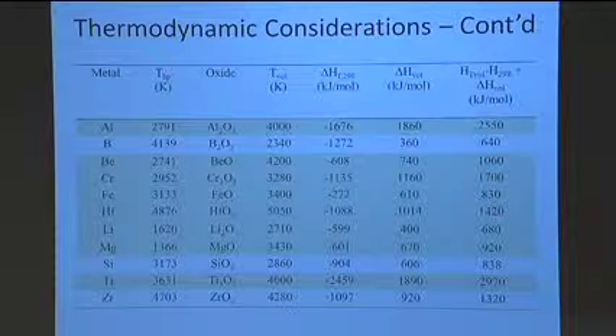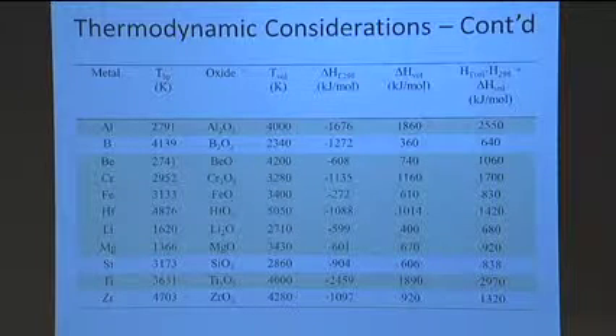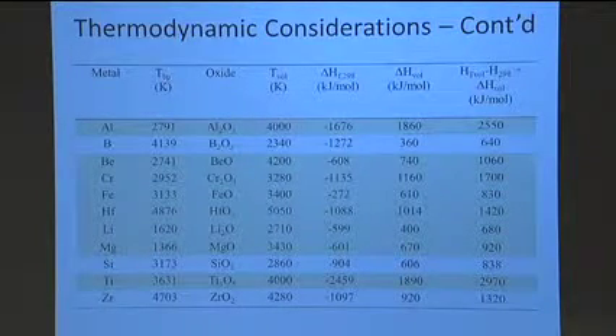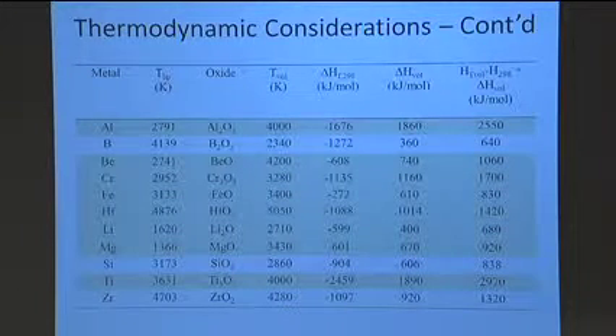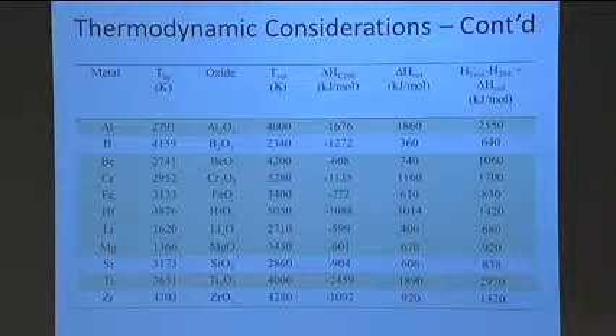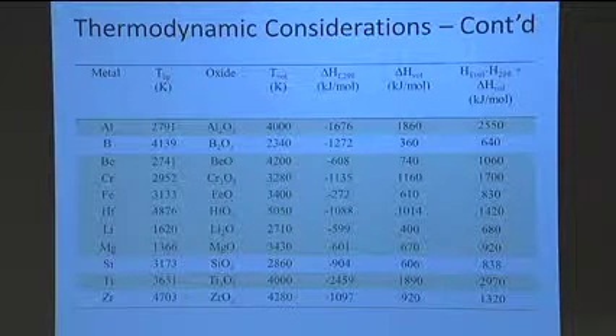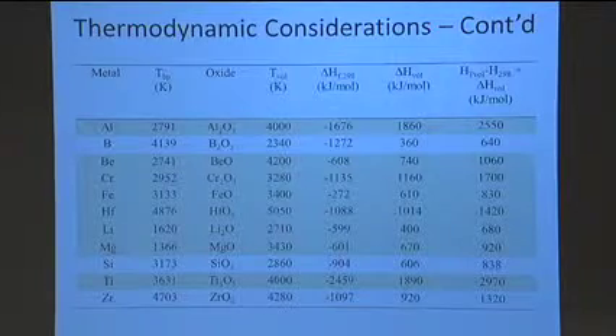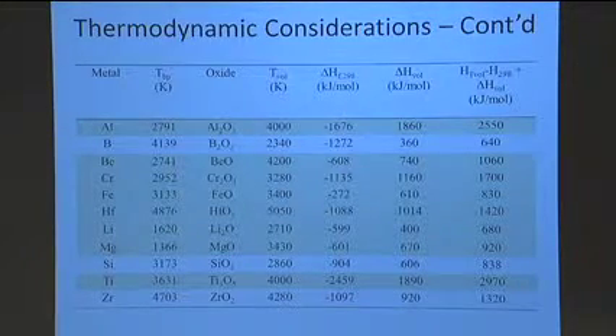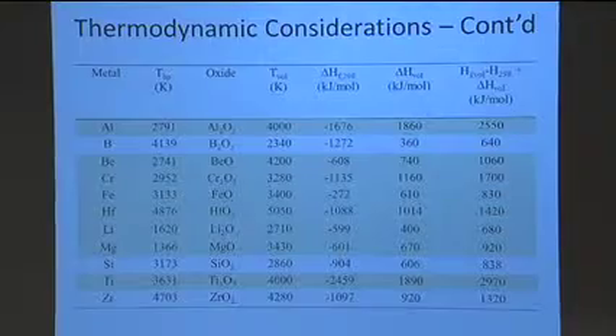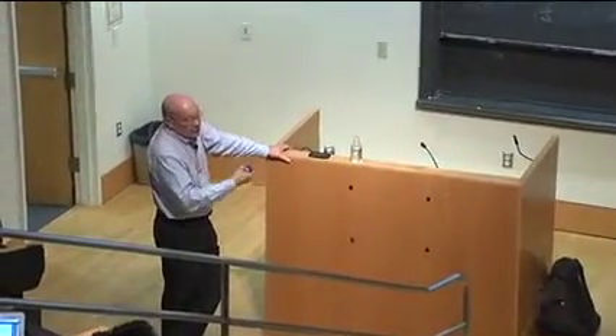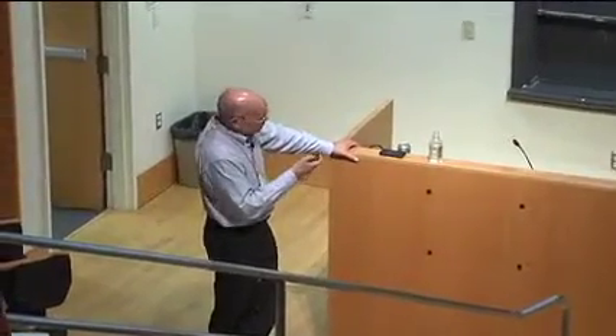Okay? And so I get a limiting flame temperature situation. And I can go down and apply this methodology to all the elements I show here. If you work through here, you'll see, for example, boron, silicon, and zirconium. If I first look at these criteria here, I have the opposite trend, which would suggest in this particular case that the boron would burn more in a heterogeneous fashion, where since I'm vaporizing the final product, I don't have enough energy to vaporize the boron itself, so it's going to burn like a carbon particle. Okay, there's going to be a heterogeneous process where reactions are potentially going to occur at the surface.